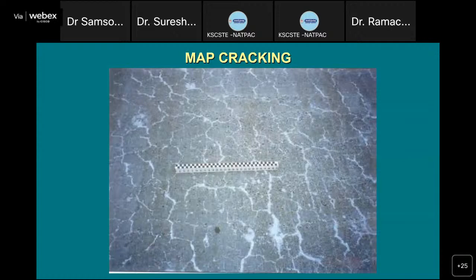Now, how do we avoid this? The best way to avoid plastic shrinkage is to do night concreting rather than day concreting. If concreting is done during the night, it will always be better. The temperature will be quite cool. If we cannot do it at night and have to do concreting during the day, what we need to do is, immediately after concreting, cover the entire road surface with plastic sheets. If you cover it with plastic sheets, water from the surface will not evaporate. Another way of doing that is by spraying curing compounds. By spraying curing compounds, you can overcome this problem. There are wax-based curing compounds. You spray it on the road, it will create a very thin wax layer, which will not allow evaporation of water. Therefore, plastic shrinkage cracks can be avoided.